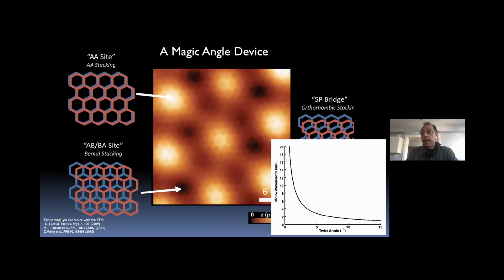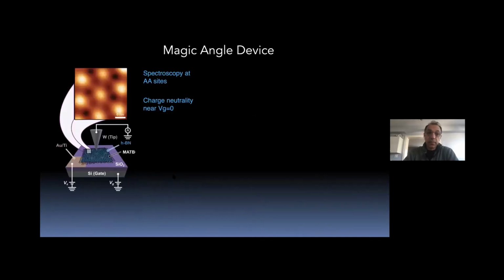So unlike our transport colleagues, we can actually directly measure what the twist angle is from the experiment, and we can also assess whether these samples, which are often created on top of a boron nitride substrate, are aligned or misaligned with the boron nitride underneath, which has its own Moiré lattice, which you can sort of see in this image right here. Okay, so now let's talk about the spectroscopic measurement.